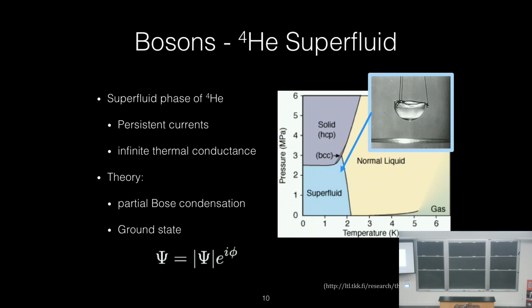So let me tell you about helium-4. Helium-4 is a great boson. It's helium. It's in the balloons. This is the pressure-temperature phase diagram for helium. When you're up here at very high temperature, you only get a gas. You lower the temperature, you get condensation of the liquid at 4.2 Kelvin. You keep going down in the liquid, and there's this transition to superfluidity that occurs at atmospheric pressure at 2.172 Kelvin. At that point, superfluid helium shows you persistent currents. You start to wind it up in a circle, let it flow, it'll flow forever. It has infinite thermal conductance as well.